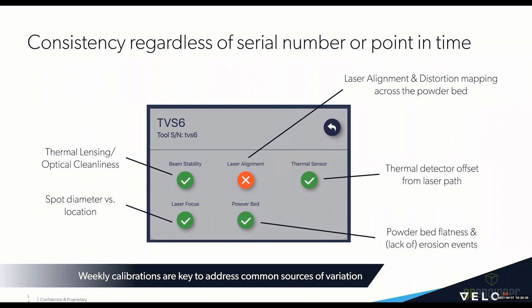And then finally, we have some really unique capabilities relative to the powder bed verification. So first off, we have a 3D topographical map of the powder bed that oftentimes we call height mapper. We can use this to basically verify powder bed flatness. So this makes sure that you have a consistent layer of powder across the powder bed, which is important because basically the powder is your feedstock in a welding process. So you need to make sure you have a consistent amount of feedstock as you're welding.